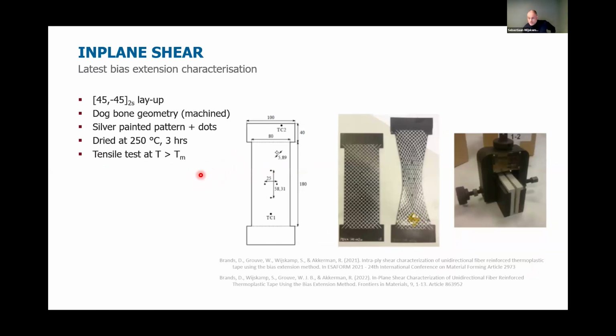So Dennis Brands, one of our researchers, thought, I'm going to give it another try with the bias extension test. We also learned that with certain thermal treatment, we were able to limit or even prevent the deconsolidation of unidirectional laminates. So drying for a bit longer time at higher temperature really helps to get the coherence of the material and no delamination.